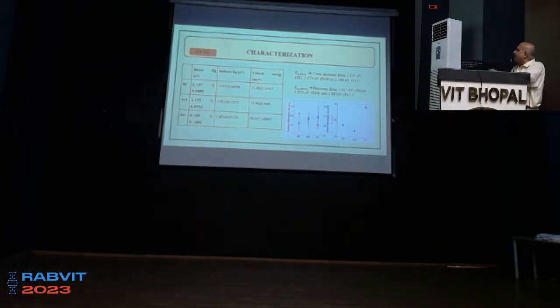But interestingly, the Urbach energy, I cannot take the class here, but it relates to the dislocations or the disorders in the material. Okay. So if you have a disordered system, a crystal is an extremely ordered lattice. If you create a disorder in the lattice, it will obviously have changes in the electronic properties, and this is where it shows up. So you can calculate the Urbach energy, and you can see that the Urbach energy is the lowest at S10. So there is something in this S10 sample which is different than others.